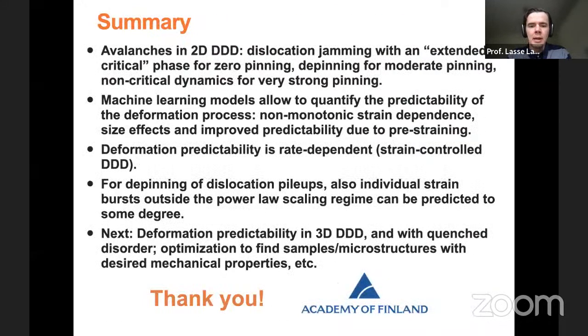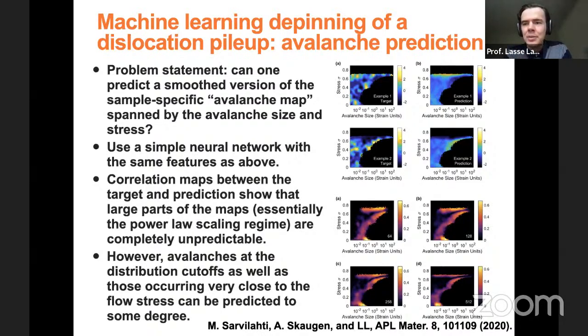Then as a final thing, I will briefly mention that we also tried to predict these individual avalanches for this specific system. Of course, I argued before that this is an inherently hard task. If you have a critical avalanche, it doesn't really know how large it's going to be, so it should be difficult to predict. So what we do here is we try to predict something that we call an avalanche map. Here is a 2D heat map spanned by stress and the avalanche size, and the color indicates where you got avalanches in the specific realization of your system.